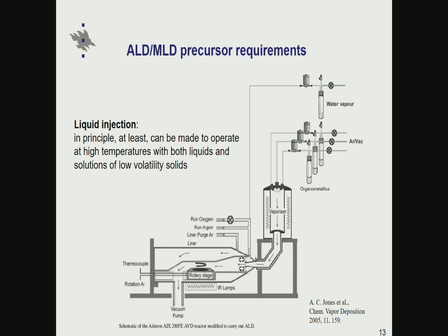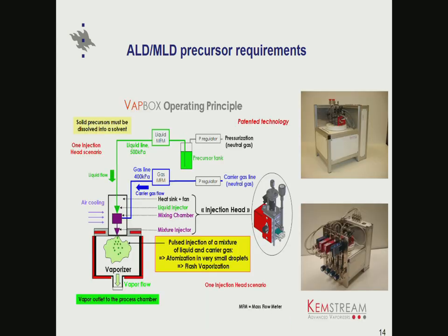Yet another way to deal with these low volatility precursors is liquid injection. If talking about a low vapor pressure solid, one chooses a proper solvent in which this compound is dissolved, and then this solution is injected into a heated vaporizer where both the solvent and the compound itself evaporate, and are then transported further to the substrate. In principle at least, one can then use reasonably low volatility compounds. There are some problems, of course, related to the fact that one still has these low vapor pressure solids there, and there may be a number of issues. Anyhow, these liquid injectors are also commercially available, and I think we will hear more about these later today.